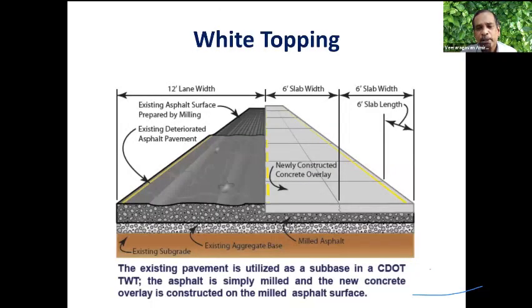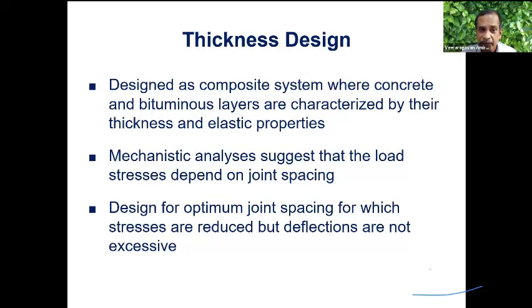White topping, we have brought in the importance of white topping in the urban roads. When the road is bad or a bituminous pavement, I can construct a white top pavement. Thicknesses can vary. It can be conventional white topping, thin white topping, or ultra thin white topping. So definitely for sustainable road infrastructure, white topping is going to be the order. Mechanistic empirical analysis suggests the load stresses depend upon joint spacing. So the rule of thumb is: thicker pavement, larger panel size.